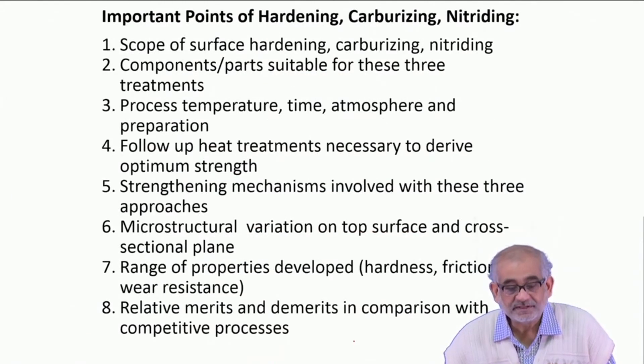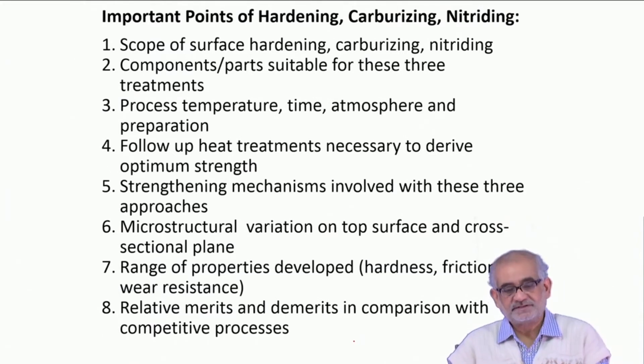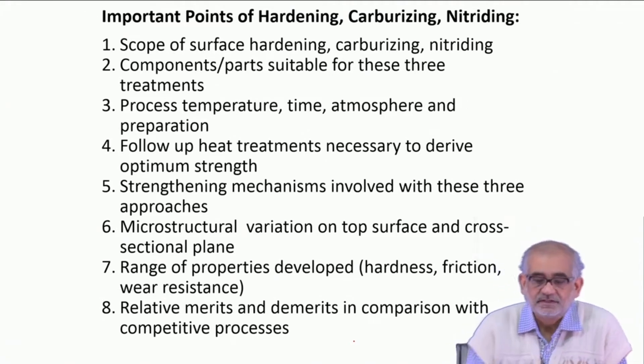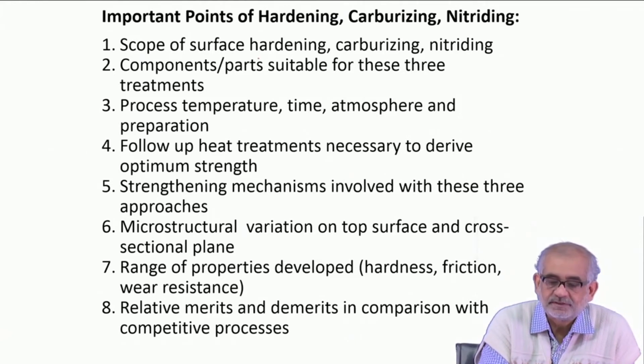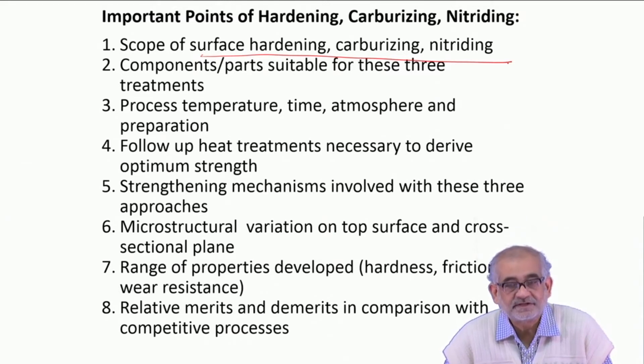It is also time to take an overall view of all the possibilities of hardening that we have discussed so far with regards primarily to steel. We have discussed three types of approaches: hardening, carburizing, and nitriding. Hardening is without change in composition - it is simply microstructural modification. Carburizing and nitriding are thermochemical treatments where we change the composition of the surface: in carburizing we introduce carbon, in nitriding we introduce nitrogen.